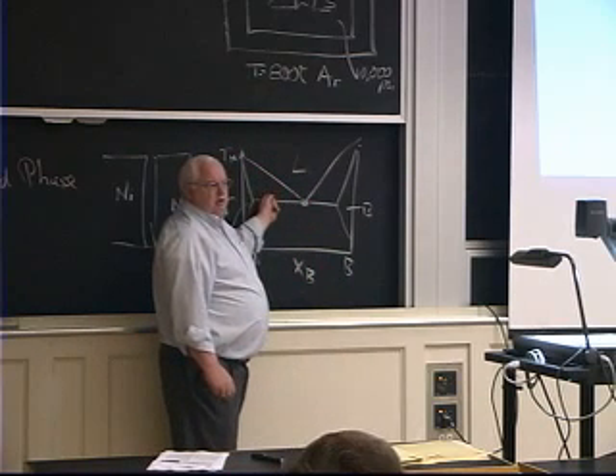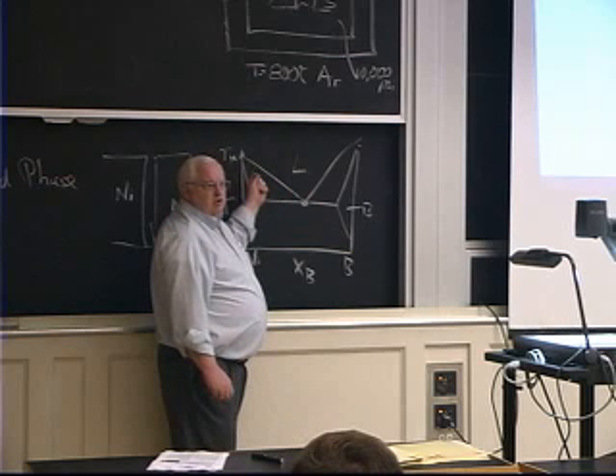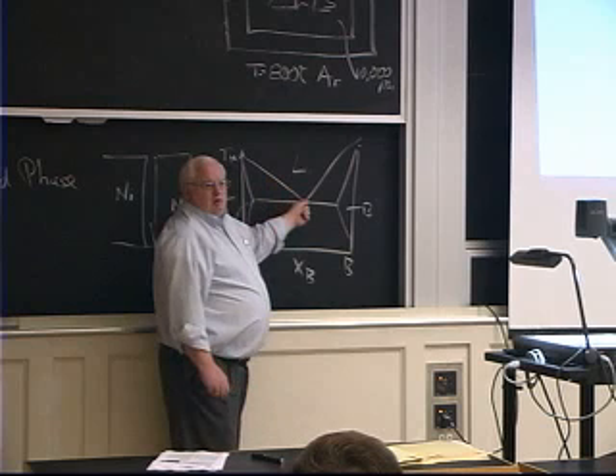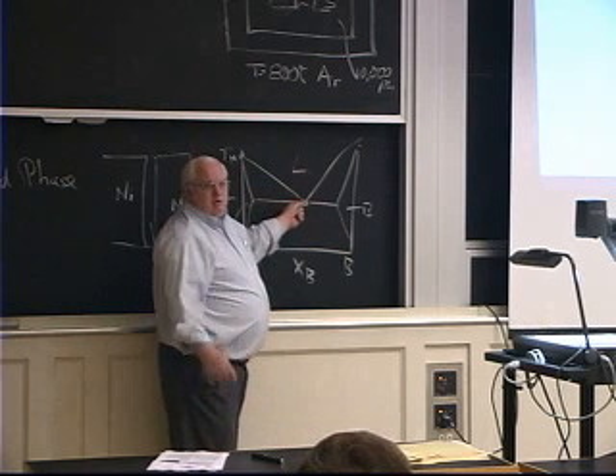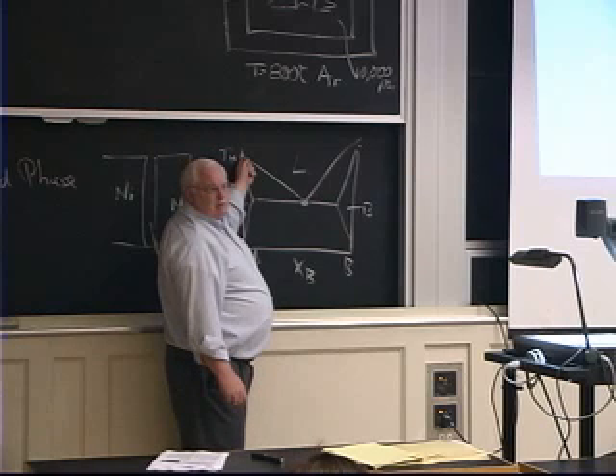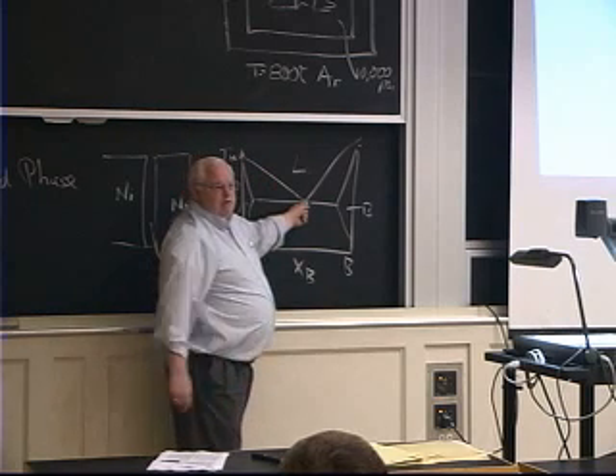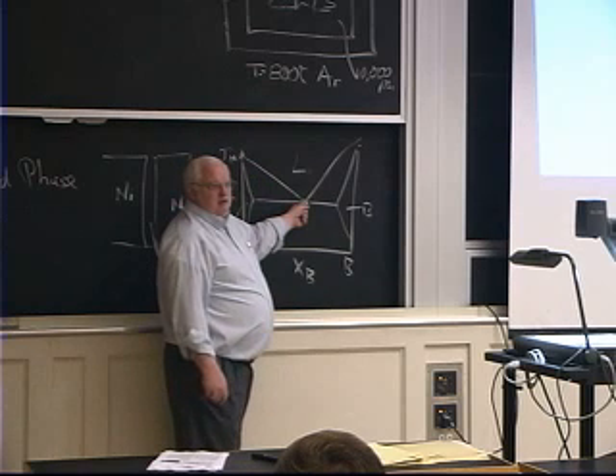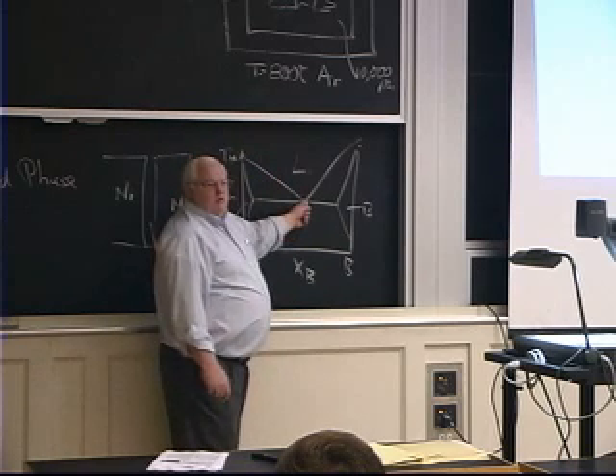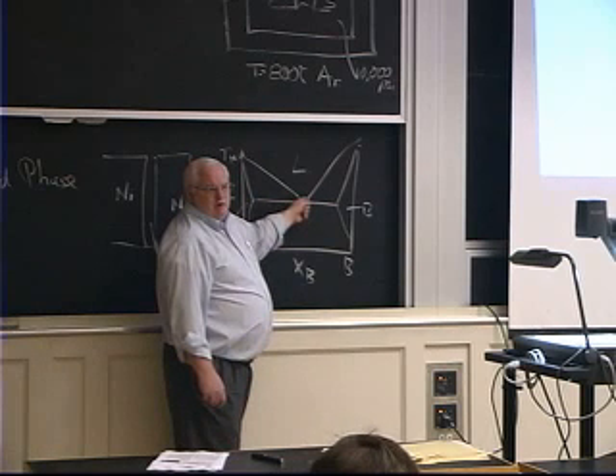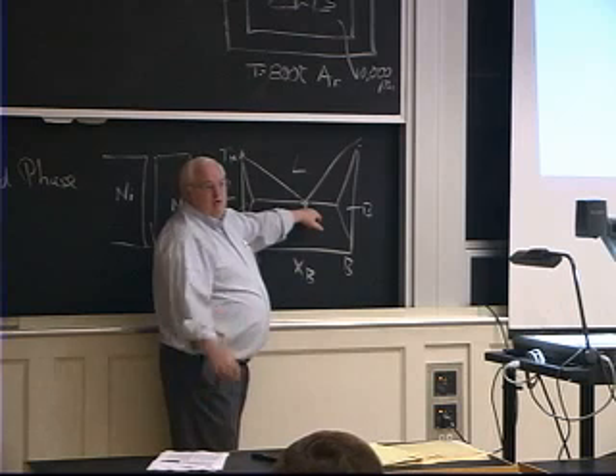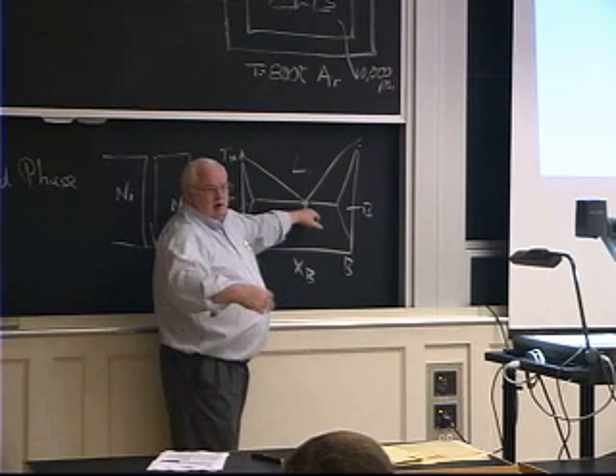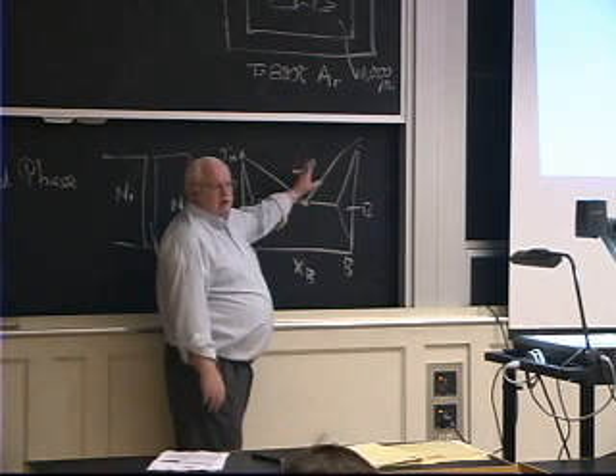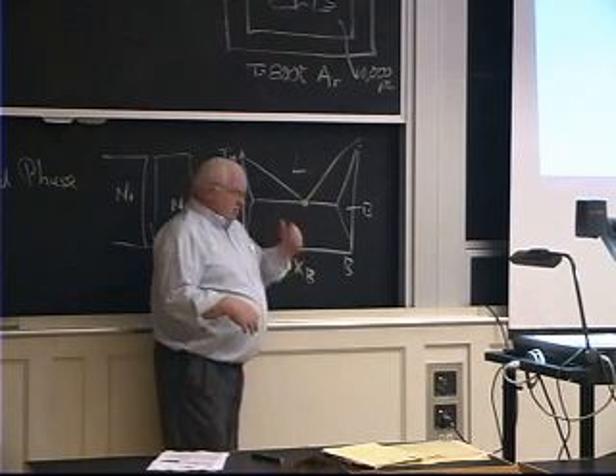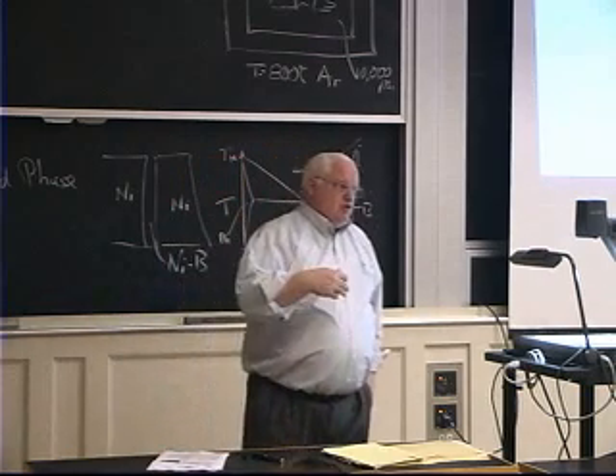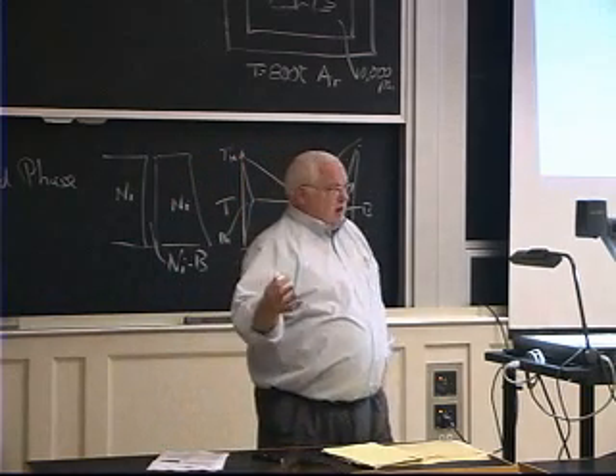Another diagram that looks very similar to this that you know of, and some of you who lived in the north have already used in your life, is the ice-salt phase diagram. Okay? You throw salt on the icy sidewalk, you've got solid ice, which melts at 0 degrees centigrade, and salt water, you guys should know this, melts at a lower temperature than 0 degrees centigrade. Depends on the salt concentration, okay? But you will form what we call eutectic, okay? And eutectic is Greek for low melting. At a certain composition, if you've ever made your own ice cream, if you live in the South, you put salt on the ice in an ice cream freezer, and that's what lowers the temperature, and you extract the heat of fusion from the salt water. And that extraction, actually you absorb the heat of fusion as you melt the salt water. It has to absorb the heat of fusion.